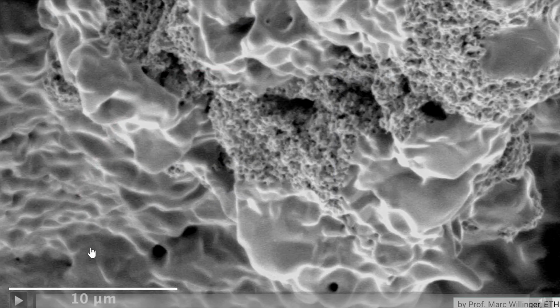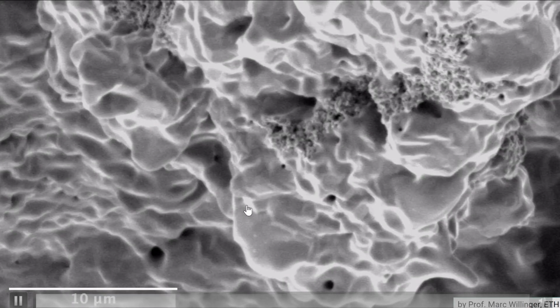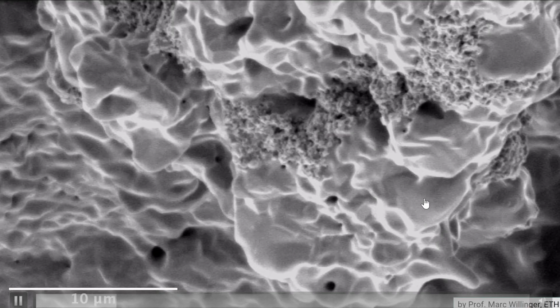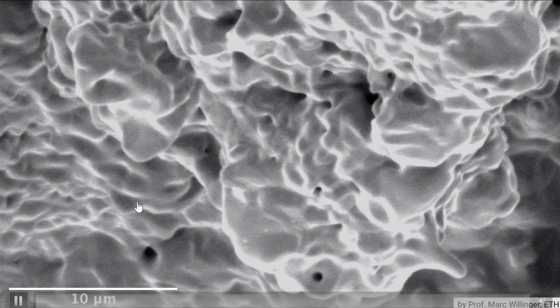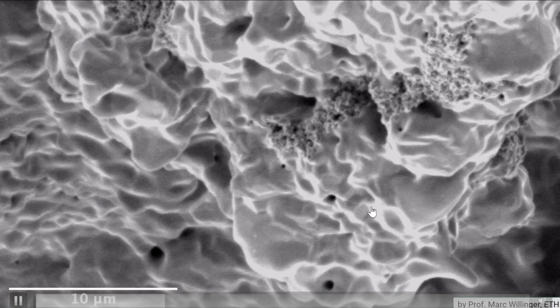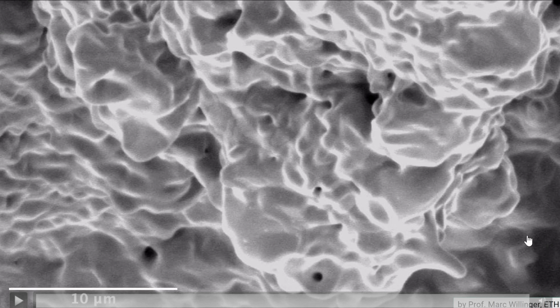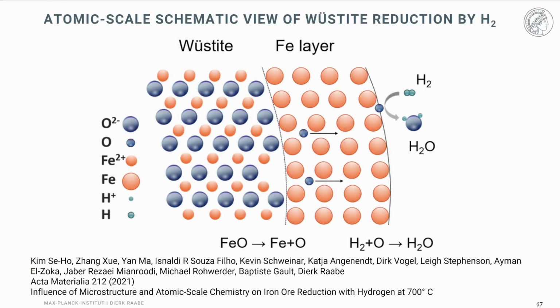So here's a very nice environmental microscopy observation from our colleague Professor Mark Willinger from ETH Zurich. And you can see here that a film of iron is formed on the oxide. Below is the coarser oxide, and on top of that, when you expose it to hydrogen in the electron microscope, you see how this iron film forms. That also means that further hydrogen or oxygen transport in the other direction must go through this iron layer. This is shown schematically here. That means the oxygen from the wüstite must escape through that iron layer towards the surface, where it can recombine with hydrogen to form water. This is the current picture that we have about this process.